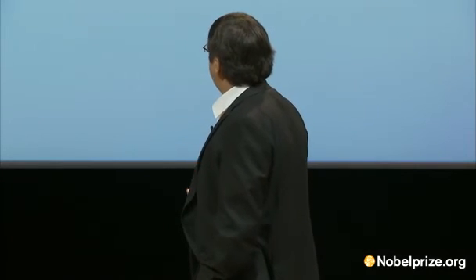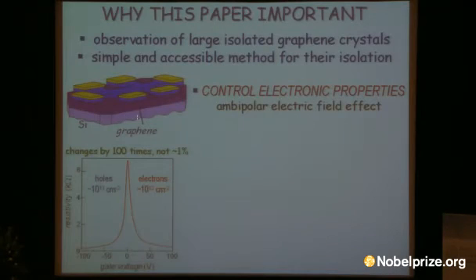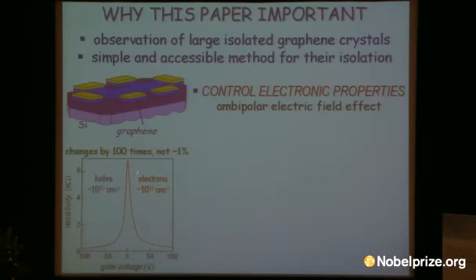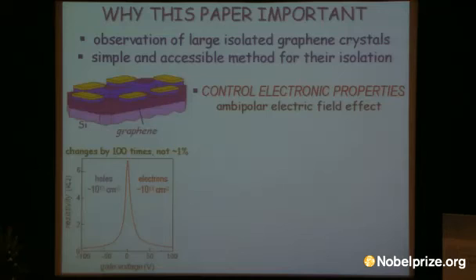What we did, we found out that with the gate, with a change in voltage on the substrate, we can change the properties of this material. Take a film of gold. Whatever you do, it will be a film of gold. Here, with an external electric field, we change graphene from a metal which has a lot of electrons to a good metal which has a lot of hole carriers, through a regime where it behaves like a semiconductor. It's a lot of properties within the same device. We called it the ambipolar electric field effect. And the changes are huge, not 1%, 100 times already in this paper.